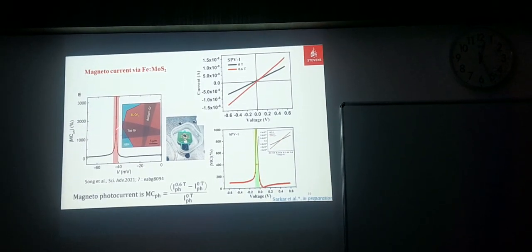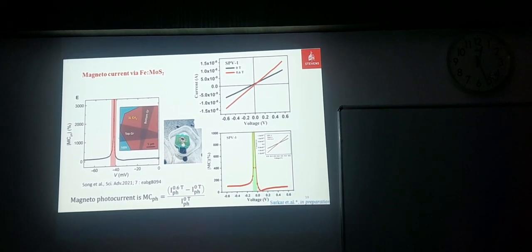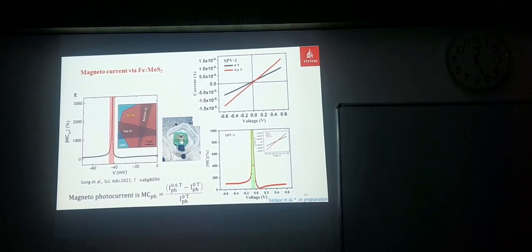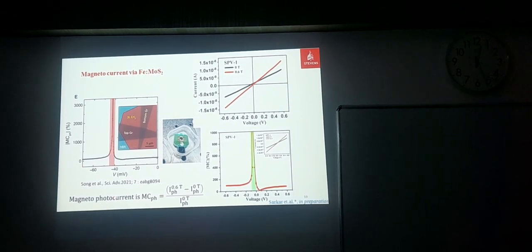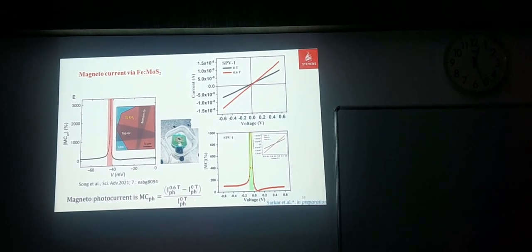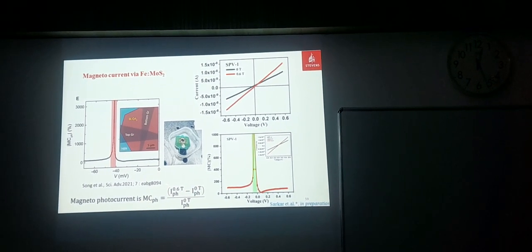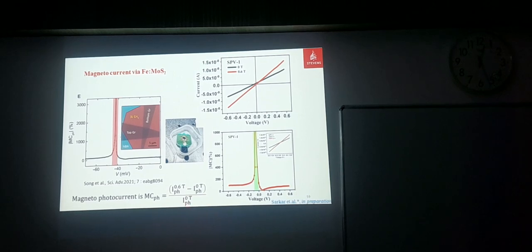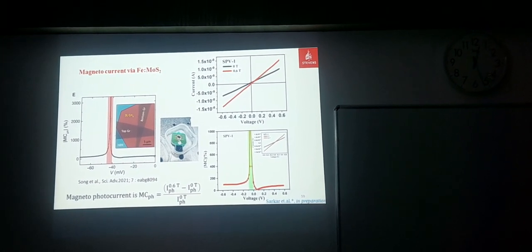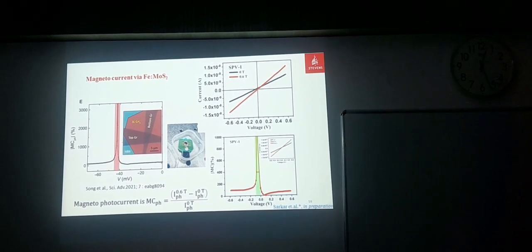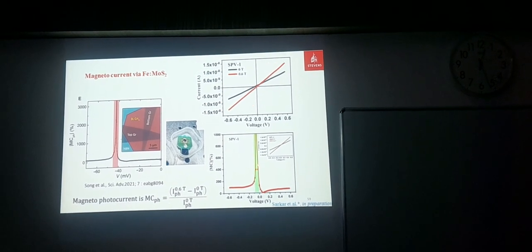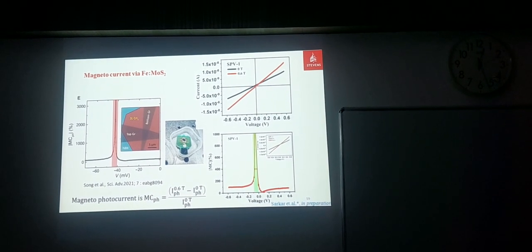Now the important part, if we talk about the magnetic system for spin photovoltaics: we talk about the magnetophotocurrent of the system. This is basically a measure of the difference between zero magnetic field and a certain magnetic field, divided by the zero-field value. At a certain voltage, you might have a huge change in magnetoresistance. This is one published paper in Science Advances in 2021. We have also observed something similar in our system, around 40 millivolts, but at a much higher elevated temperature than this one.